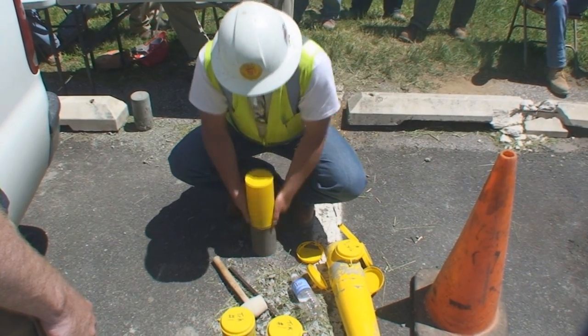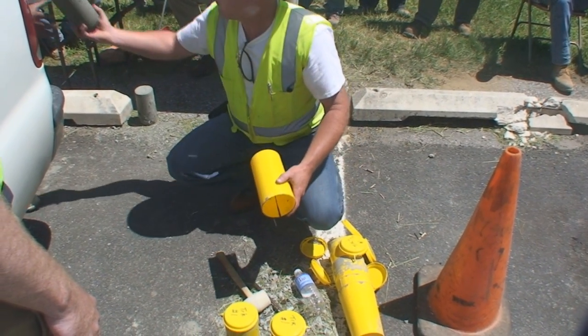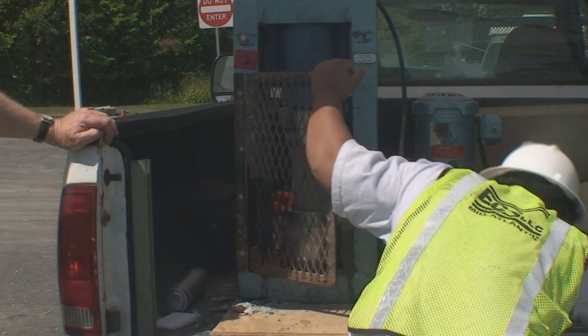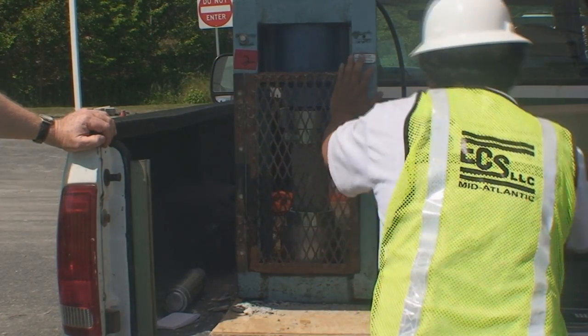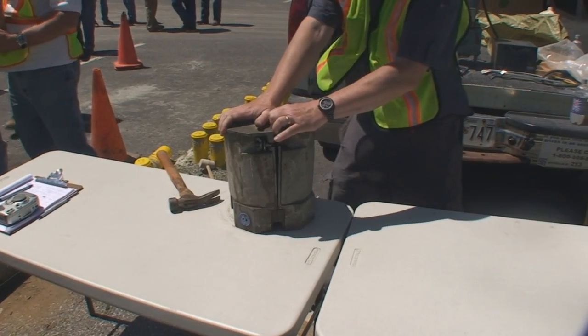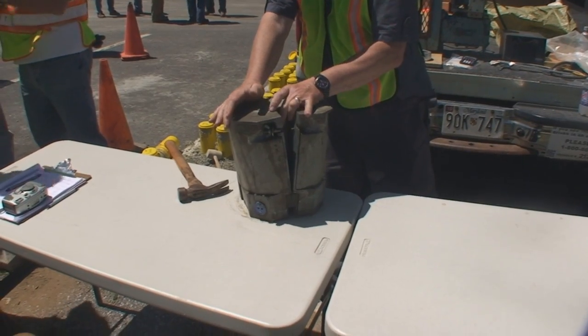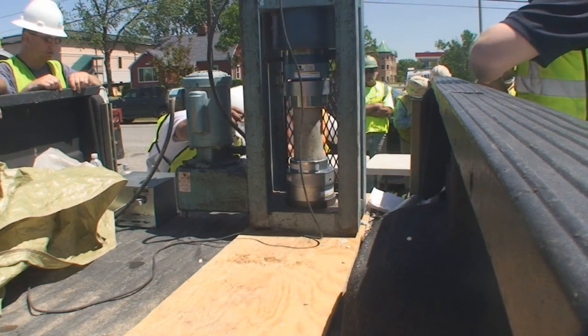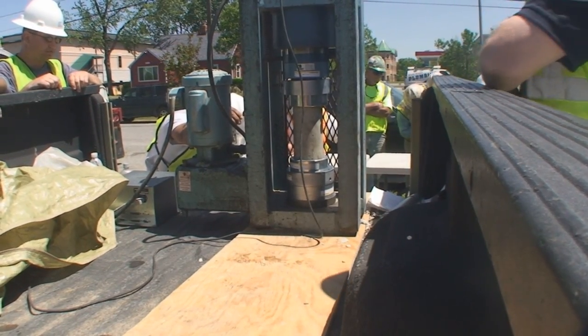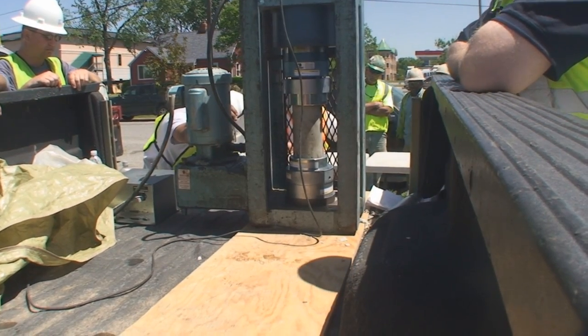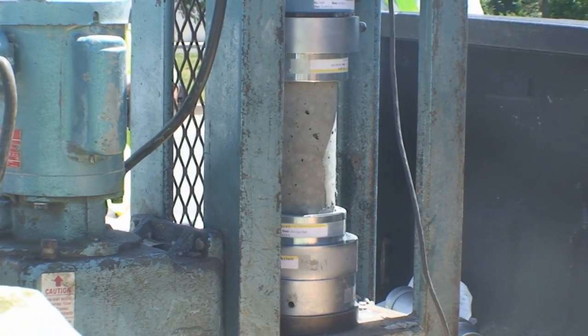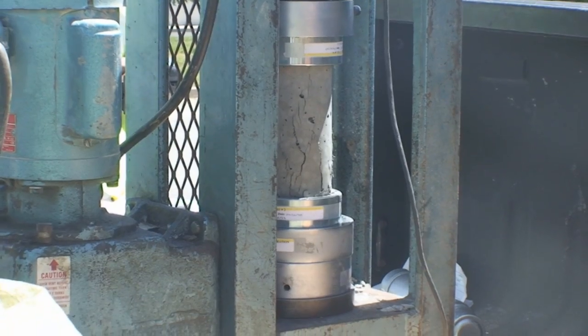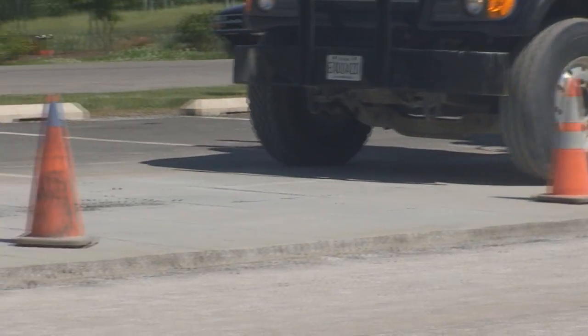After 3 hours, an on-site break machine began tests of the compressive strength of the concrete. As the strength increased toward 2,000 PSI, cylinders were broken at shorter time intervals of 30, 15, and 10 minutes, with the concrete achieving over 2,500 PSI within 3 hours and 52 minutes of placement. Only 7 hours and 45 minutes after closure, lane 1 was reopened to simulated traffic.